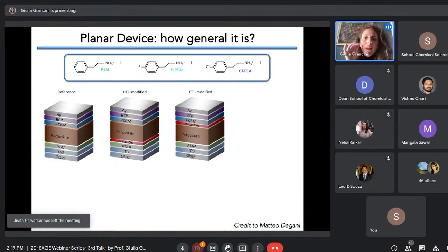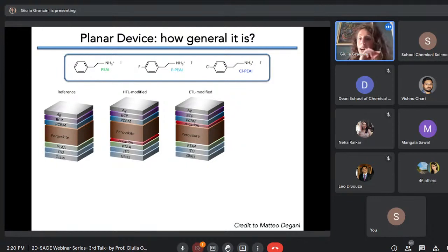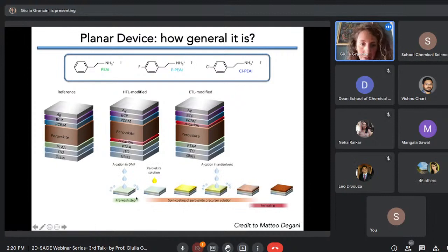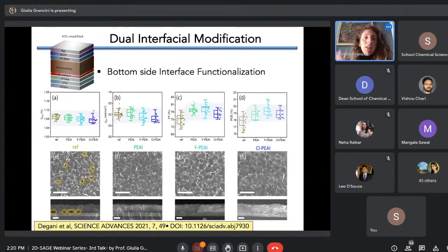In this case, we are using only a tiny amount of these phenylethylammonium cations to have a surface passivation without the formation of a net 2D perovskite layer. To do that, we invented a method to basically insert these phenylethylammonium cations at the bottom surface of the perovskite. And then we combined both the approaches with a simultaneous bottom and top passivation. Let's look at the bottom interface first. With the bottom side functionalization, what you can clearly see is that the morphology improves.